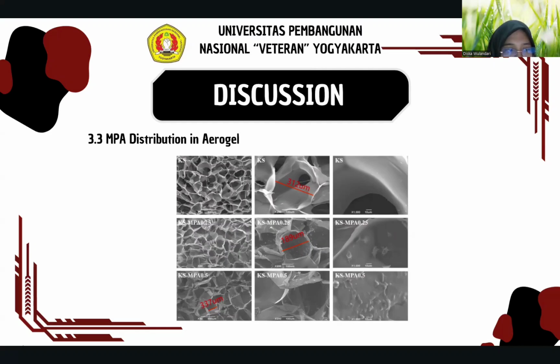Upon adding MPa, the pore structure became more irregular, due to the hydrophobic effect of MPa inhibiting ice crystal growing during the freezing process. At MPa concentration above 0.5%, nanosheet adhere strongly to the aerogel pore walls, causing structural damage.